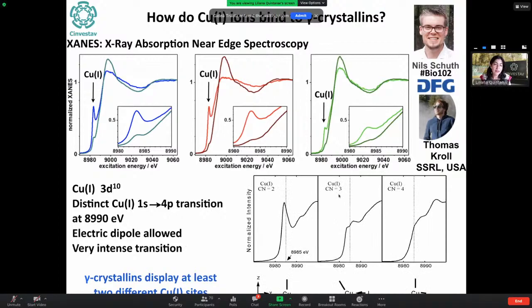So the d shell is completely full. So then we extract an electron from 1s and it goes to the 4p orbital. And we now know from the work of Solomon and Keith Hodgson at Stanford that these very sharp features in the pre-edge for copper-1 are ascribed to having a bicoordinate type of coordination. So it yields a very intense electric dipole allowed transition. So in all cases, we can see copper-1 species in the proteins.